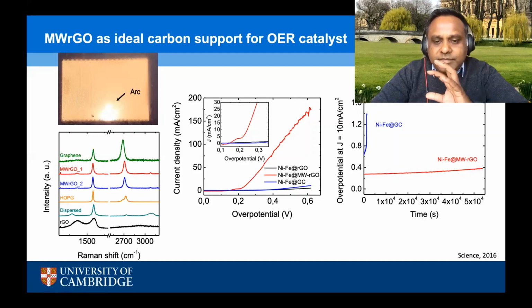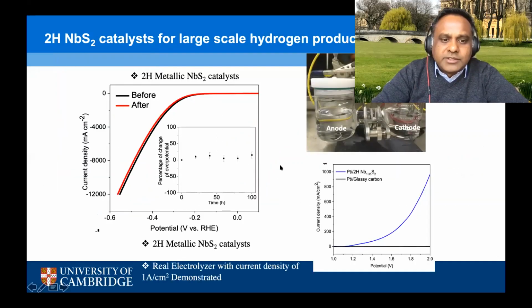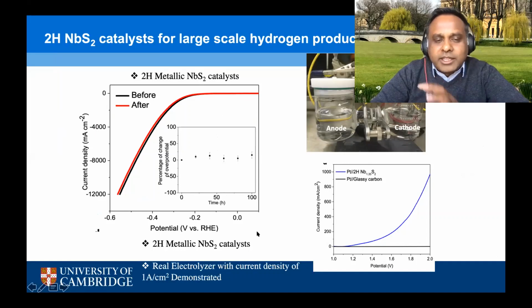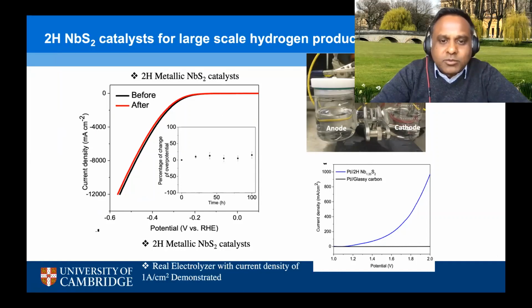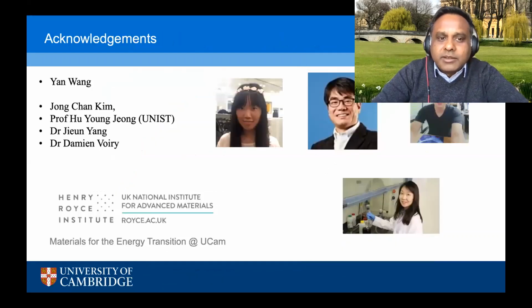So this contact is not only important in transistors, it's also very important in electrocatalysis. And very recently, we published a paper last year where we showed that we can take these metallic TMDs like niobium disulfide, and we can build an electrolyzer for splitting water, and we can achieve current densities that are of the order of 1 amp per centimeter squared. So this is real electrolyzer current density. So I'm not going to talk too much about electrocatalysis, but I just wanted to give a flavor for how the contacts work is related to lots of other things as well. So with that, let me conclude and perhaps take a few questions.